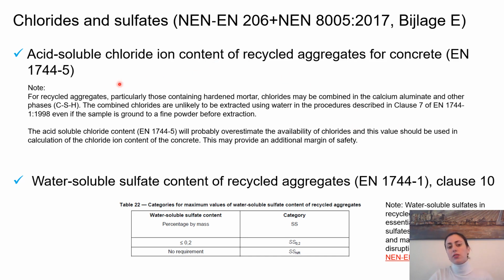So we studied acid soluble chloride ion content because, even though it overestimates the chloride content in concrete, it gives an additional margin of safety, and it should be used in calculations of the concrete mix design. While for the sulfates, we should use the water soluble sulfates, since acid soluble sulfates are not that common. The water soluble sulfates are the main ones that should be checked for expansive reactions that could occur in concrete during the service life.